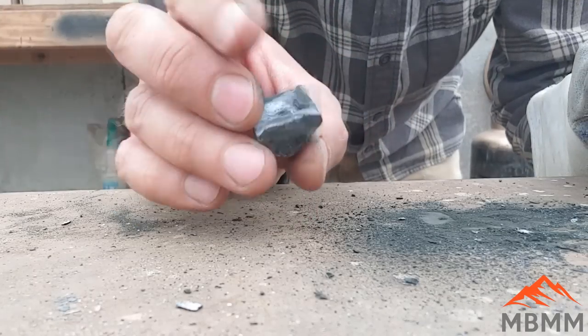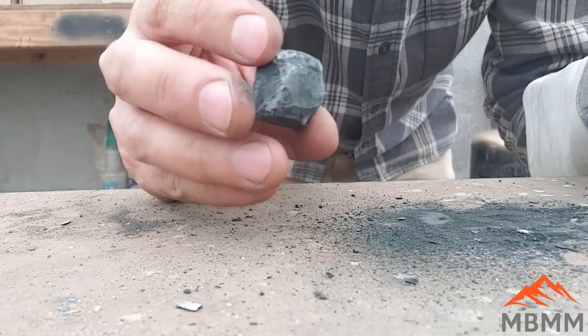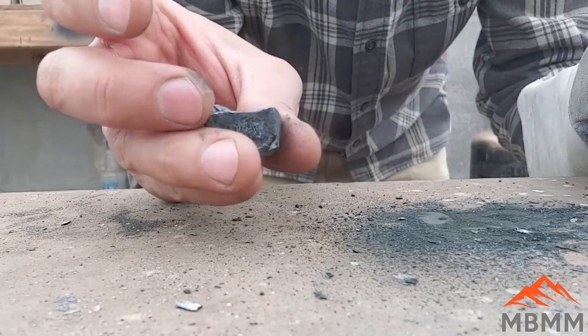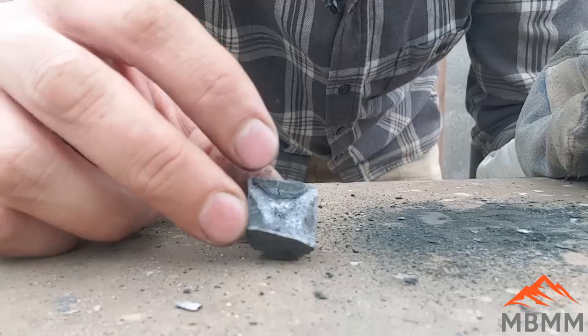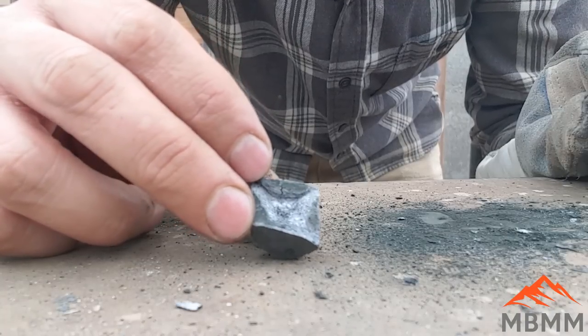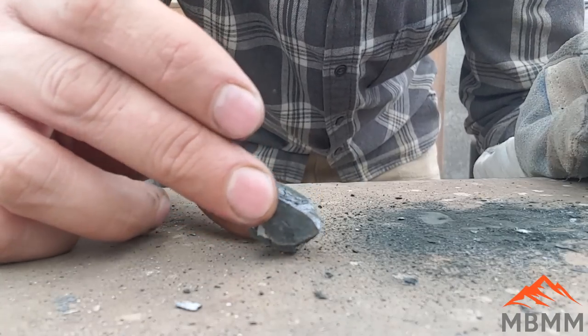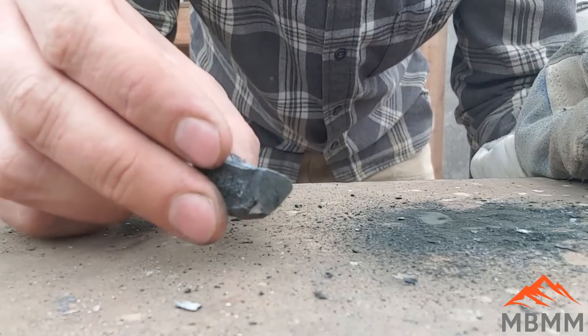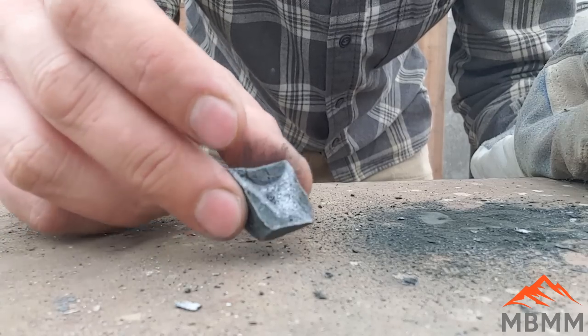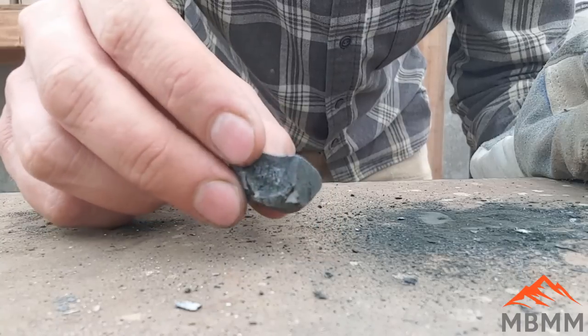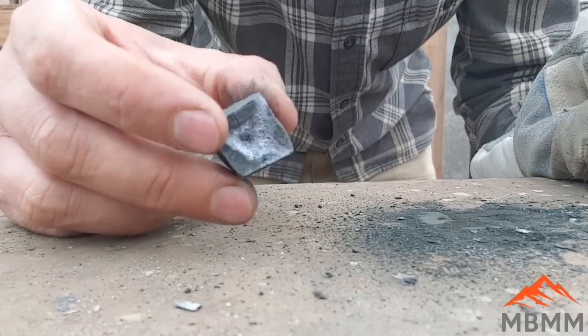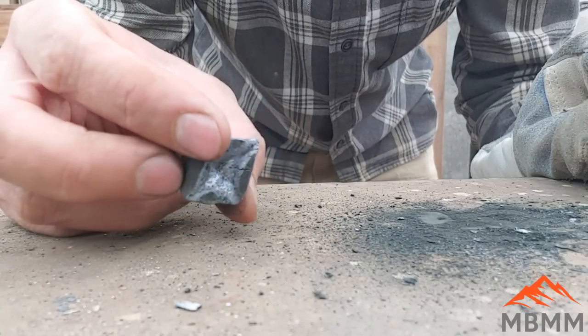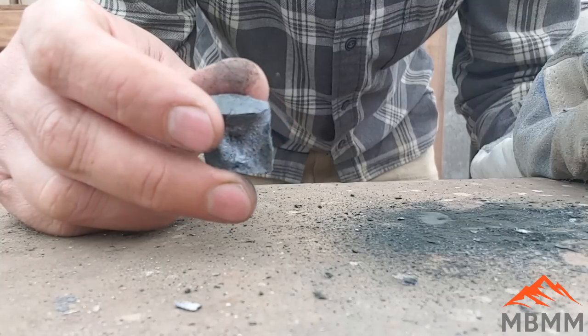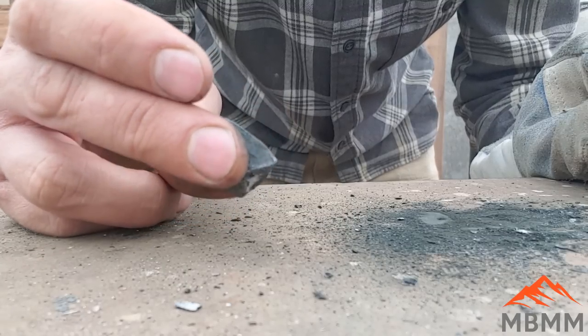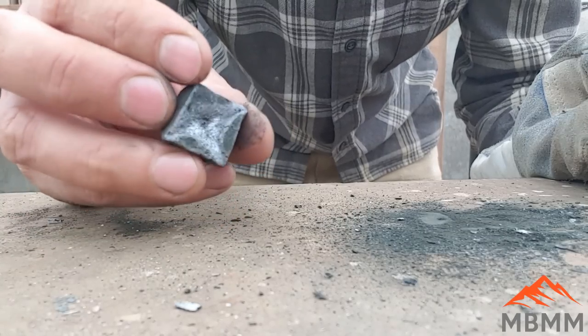So there's our little lead button. I've knocked pretty much all the slag off it, but it's really hard, and you can see right there, it's cracking, which tells me there's a lot of other metals in there other than lead. If it was mostly lead and gold and silver, it'd be real soft and I could hit it. But that iron rod probably reduced quite a bit of copper or maybe some other metals in there that are making it hard and brittle. So we'll see how this cupelling process goes.